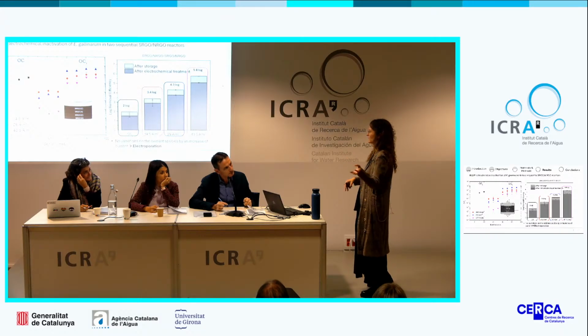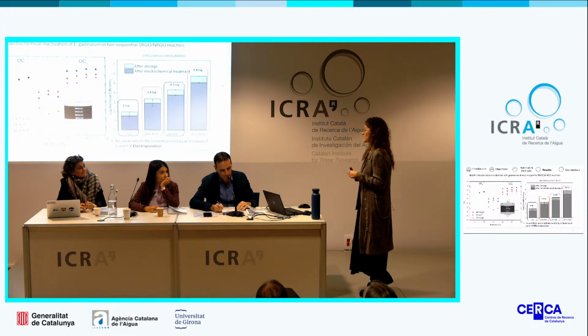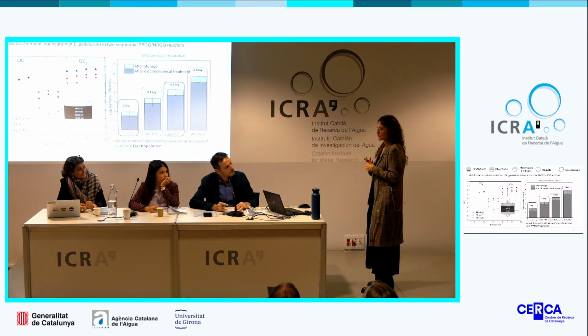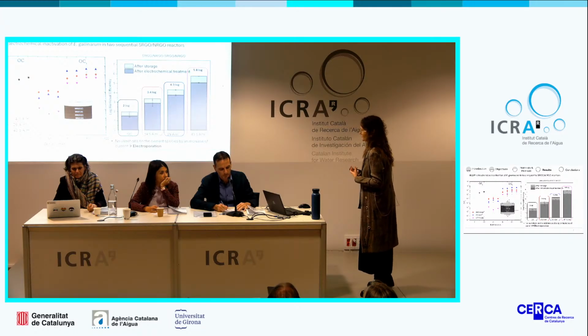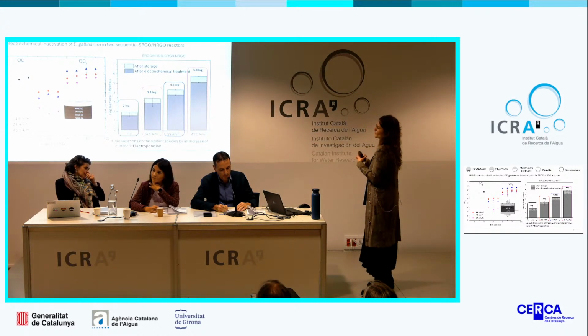First, we did it in the past when we were starting with these materials, and we were measuring the chloride at different currents and also in different flows, from the anode to the cathode and from the cathode to the anode. And the quantity, if I'm not mistaken, in the case of anode to cathode, was 0.1 milligram per liter. It wasn't a significant quantity. So according to this result, we decided to continue with this synthesis and these electrodes.